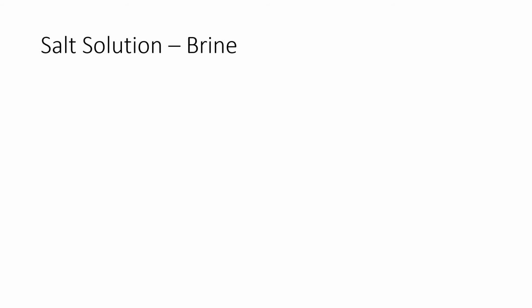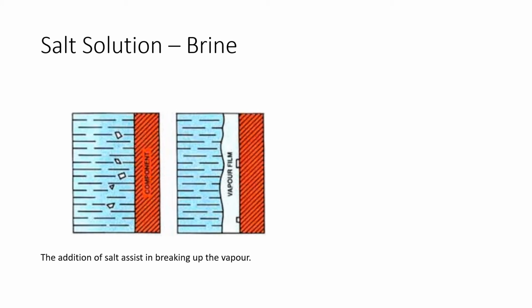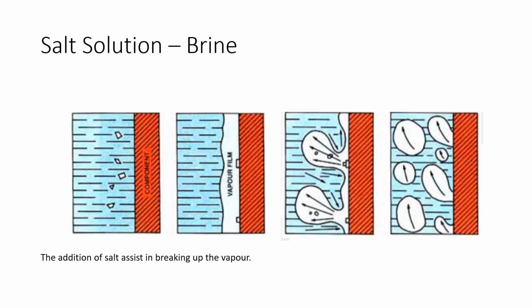Quenching in salt water or salt solution often will result in steel with the highest hardenability. Why? The addition of salt will assist in breaking up the vapor blanket, and therefore the quenching medium will come in contact with the hot surface of the metal quicker. During quenching, crystals of salt are deposited on the surface of the steel. The localized high temperature will cause these crystals to fragment violently, and this will create turbulence, which will destroy the vapor film, and this will give the highest maximum cooling rates.